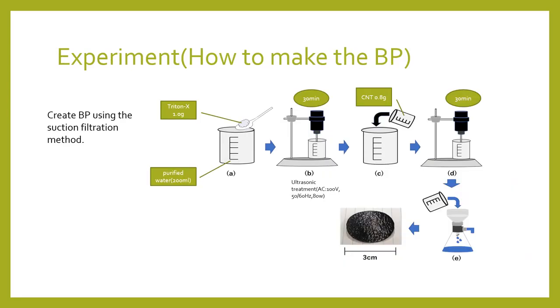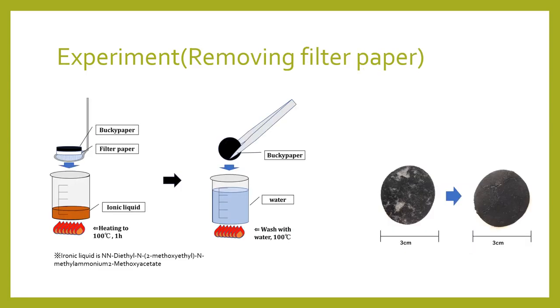Next, I will explain how to create buckypaper. Buckypaper was prepared using suction-filtration method. It was made by dispersing CNT in an aqueous solution and passing it through a filtration filter. Buckypaper peeled from the filter paper has cellulose on it.